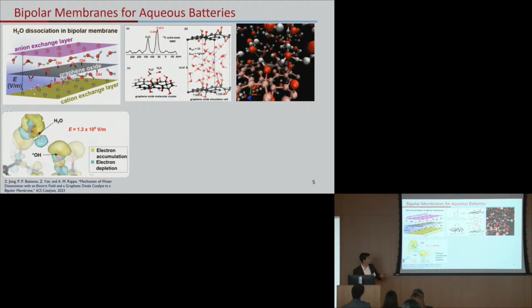And from these results, we were able to find which exact active sites on graphene oxide were really best for enhancing this water dissociation. And then from the DFT results we have down here, we can see the effects of the electric field. So why was an electric field we were finding having so much better results, like enhancing the water dissociation? And we found when we looked at the electron accumulation, depletion, and looked at those interactions at the atomic level, we found what was happening. So it was really exciting to have these results, and we published last year.